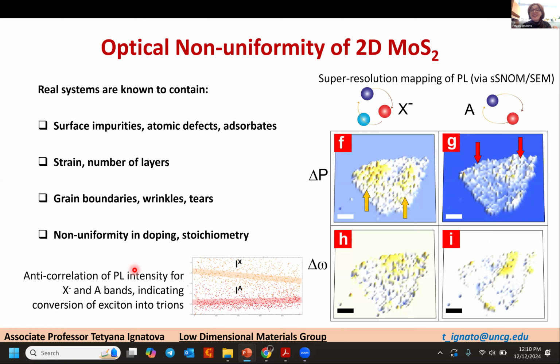Here is our data when we extracted this information, and you can see here the difference in intensities. This is information for exciton and trion, and the difference shift for the widths. By plotting a correlation between information related to exciton A and trion, we can get some correlation. This data is not correlated well. However, we can see that there is anti-correlation. Enhancement of exciton intensity will be combined with decreasing of trion intensity, which could be used in future engineering of optical properties of molybdenum disulfide by applying certain engineering procedures.